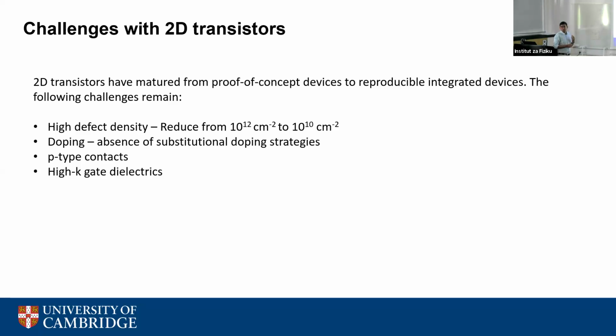Also, the other challenge is doping. As I said, in transistors, you need to make source and drain. And source and drain in silicon transistors is enabled by ion implantation. But in 2D materials, you cannot dope them by ion implantation. It's only one layer thick. So as long as you think of ion implantation, you will damage the material. So you need to find clever ways of incorporating dopants during synthesis.